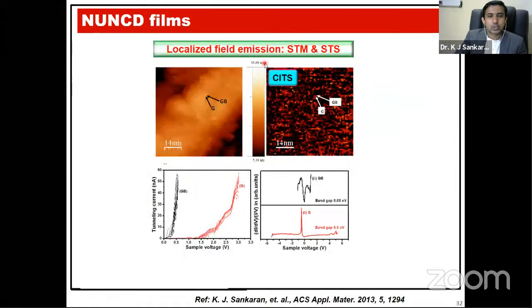What is the reason? So also to know, we used localized field electron emission studies using scanning tunneling microscopy and scanning tunneling spectroscopy. This is a very sophisticated tool that we measured at 10⁻⁶ torr in a high vacuum environment to know the localized electron emission. So we can see locally, maybe in a very nano sized region, where the electrons are emitting from, the grains or maybe the grain boundaries. So G represents the grain and GB represents the grain boundary for this particular AFM image. And you can see that the grains are the dark region and the grain boundary is the red region.